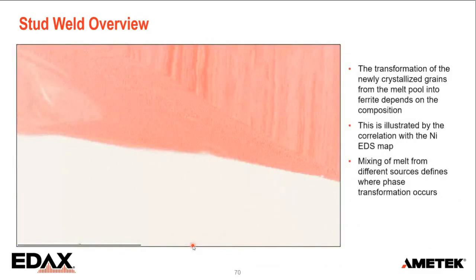Now, why did that part go back to ferrite and not the rest? That's compositional. Here I have a map where this is the nickel chemical map collected at the same time as the EBSD map. We can see the elongated banded structure from the original stud. This is the melt. And here we have an area with lower nickel, and that's just incomplete mixing.